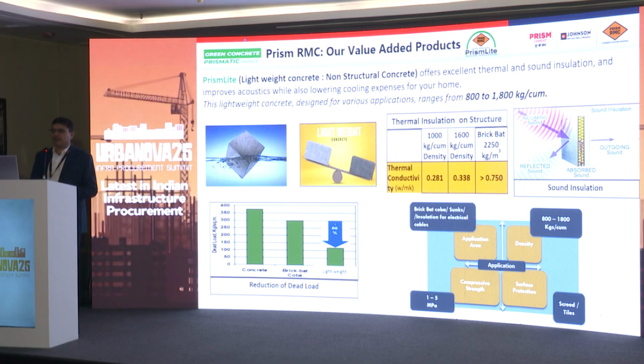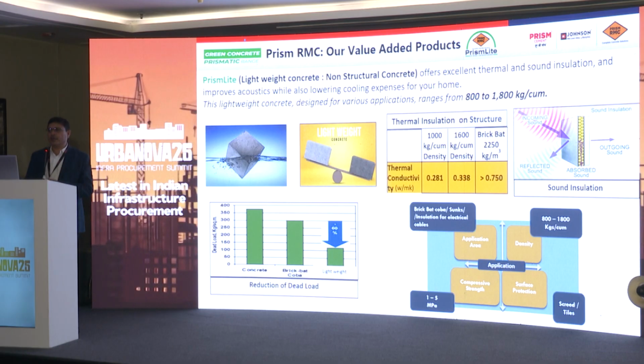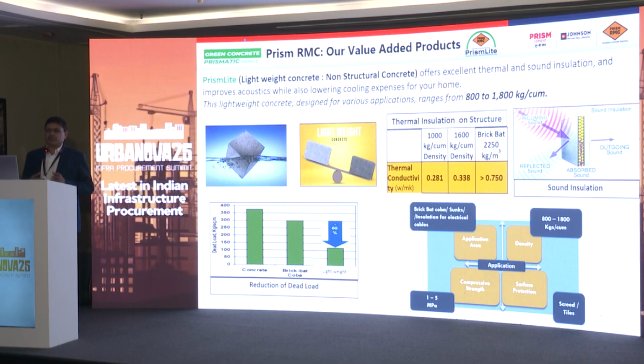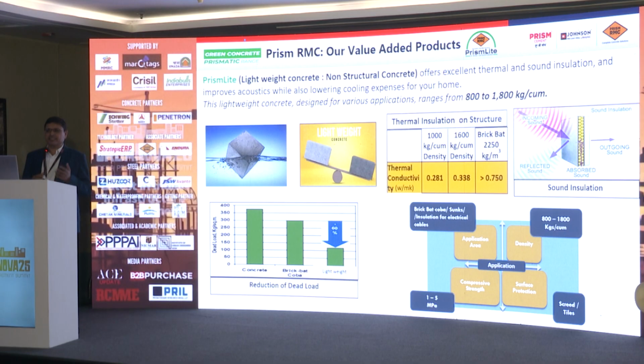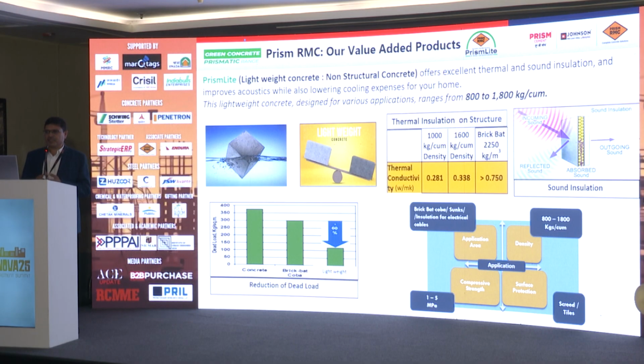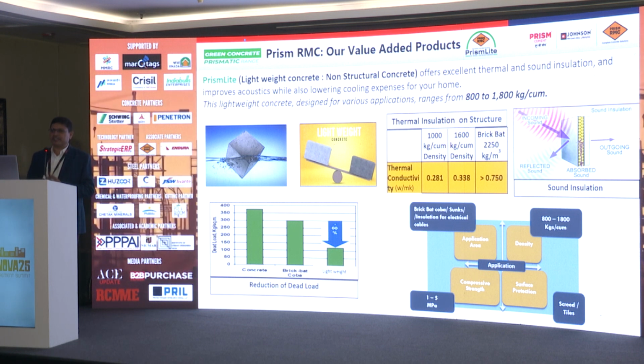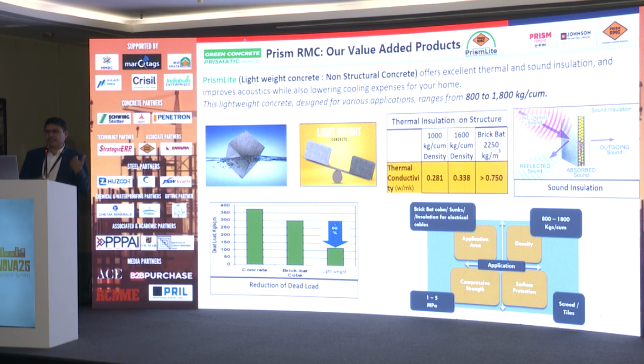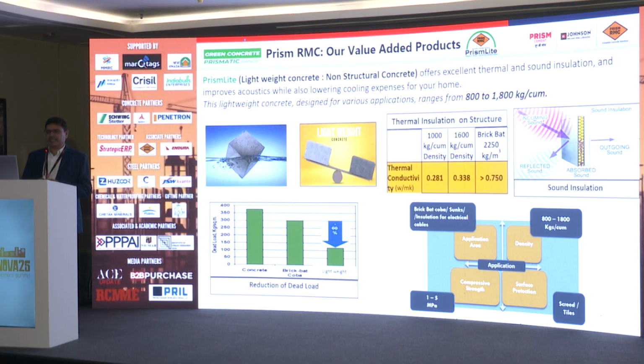Lightweight concrete has a density from 800 to 1800 kg per meter cube. The density of concrete is generally not fixed; it depends upon the specific gravity of the raw materials used. Normally, the density of concrete comes around 2500 plus minus 50 kg per meter cube, but in the case of lightweight concrete, we have less than 1800.